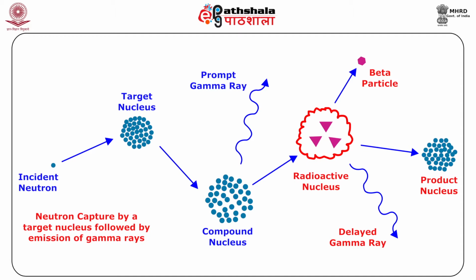To carry out a neutron activation analysis, the specimen is placed into a suitable irradiation facility and neutrons are bombarded onto the sample, allowing the elements to form isotopes. After the irradiation has taken place, the artificial radioisotopes decay with emission of particles or gamma radiation, which are main characteristics of the element from which they are emitted.